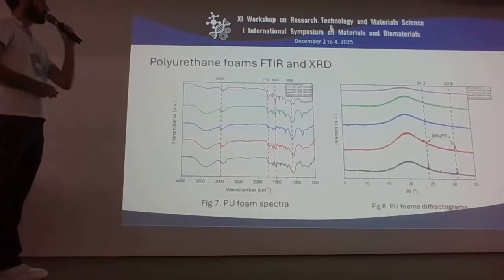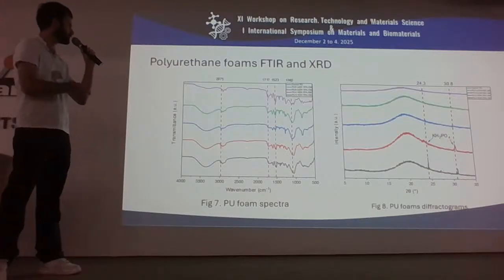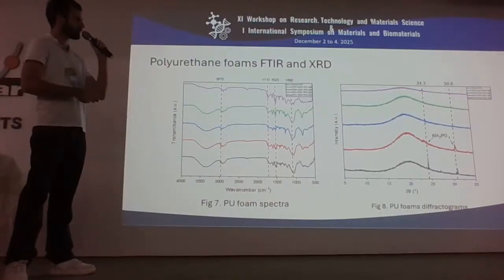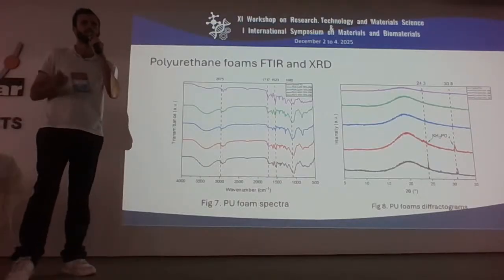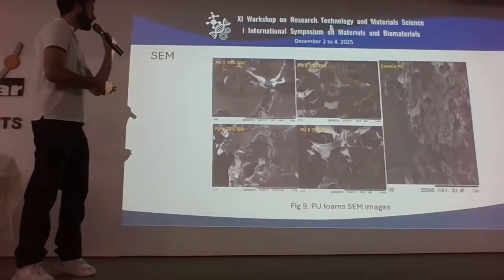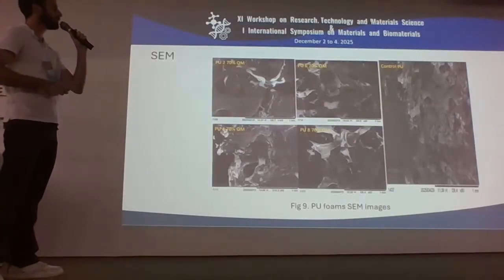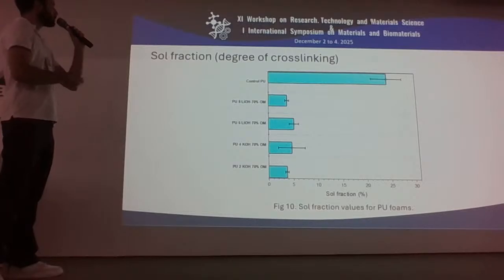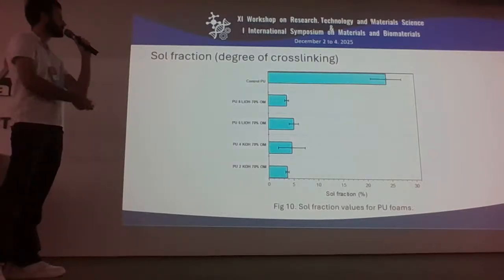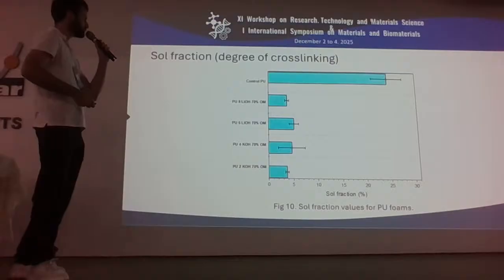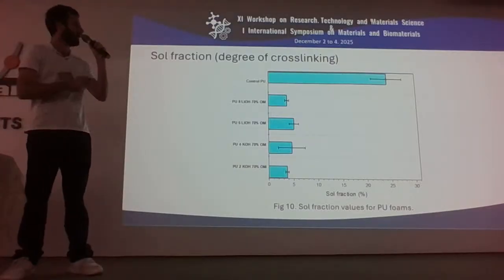So now, for the FTIR of the polyurethane foams, we can see they were successfully prepared by the appearance of the characteristic bands such as C-H bonds, carbonyls, and C-N bonds. Additionally, the XRD showed an amorphous halo around 20 degrees, which indicates a pure polyurethane foam. For the SEM, we can see that all the samples show a similar structure compared to the control foam, but with larger pores in the hybrid foams. For the sol fraction, which measures the degree of cross-linking of the samples, we can see that with the addition of 30% of the oxypropylated polyol, it shows sol fraction values around 5%, which indicates a higher degree of cross-linking.